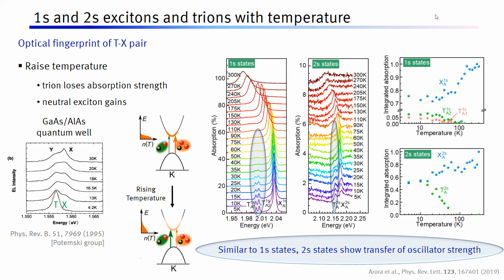The second question is, in this same slide, over a large range the peak is not shifted. No, there is no magnetic field here. It's with temperature. Up to about 110 Kelvin, there is no shift in the peak. After that, it starts shifting. So it's almost temperature independent.